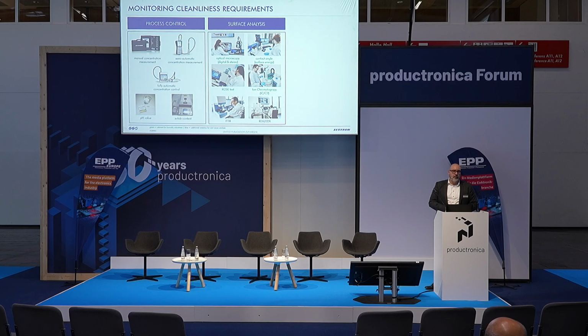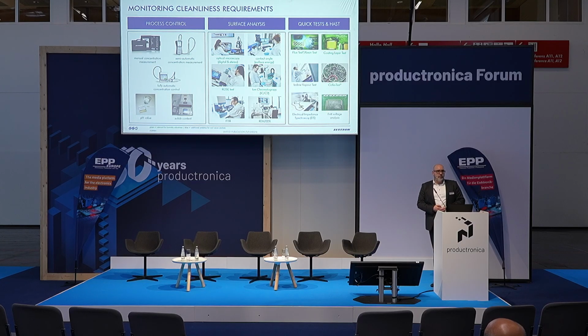So you can look at the surface, check what kind of contamination you have there, and whether it has been removed with the cleaning process. And then you can also do further validation by quick tests. This is partially easy to handle. ZESTRON invented these tests, like the flux test and the resin test, which is the same as the coating layer test, a very easy optical test where you have a test liquid that you put on your PCBA and you can check, okay, do you have some flux residues, resin residues, and you have a color marking. Or in case of the coating layer test, if you have any weaknesses in the coating layer, the test liquid can penetrate the coating and then reacts with the metal below, and you have an optical feedback if you have some weaknesses.